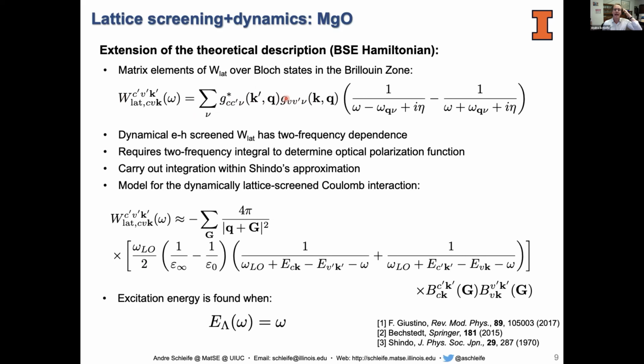So the effect that electrons, that phonons can also contribute to an external electric field. Now, that makes this frequency dependent, right? The response itself can be frequency dependent, but if you have two mechanisms for screening that appear in different frequency regimes, that in itself would make this whole screening term frequency dependent. Okay, so what we use now to incorporate into the Bethe-Salpeter approach is Shindo's approximation.